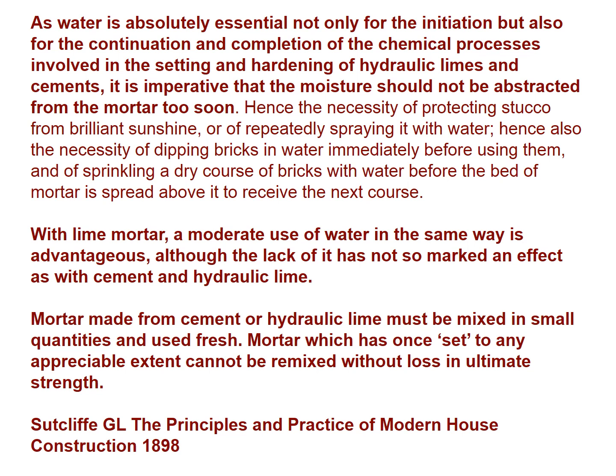Now, I hope there are people listening who might be cringing at this moment, because the ongoing hydration, one would say, if one transfers the 28-day requirement for ongoing hydration of cement mortars, when people remembered what best practice was with cement mortars, that period of initial maximum strength gain with NHLs is 6 months. And it would be arguable, indeed, to say that they need that ongoing hydration for those 6 months to set properly. If they don't get it, as Vicat observed way back, if the mortars dry too fast and dry rather than cure and set, in the case of NHLs particularly, they can lose up to 4/5 of their strength. One might say that's a good thing. They're not as strong as they might be, but nor are they set properly, nor are they what they should be.